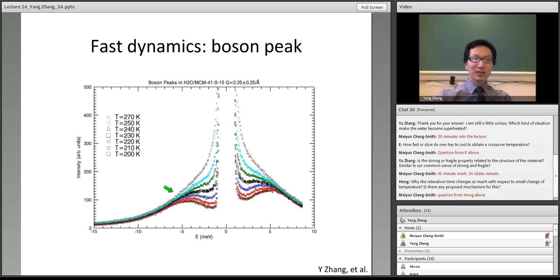So when we see a peak in the dynamic structure factor around this temperature range, it's often associated with the so-called boson peak. All those phenomena happen around the crossover temperature and above the glass transition temperature. And this is the temperature where we think the activated processes start to kick in. Okay.